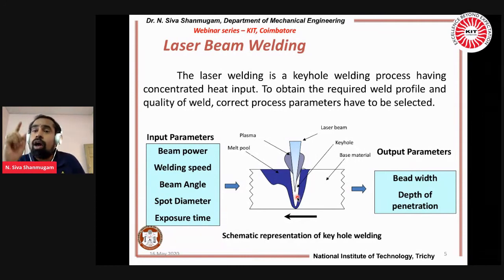10 power 5 watt per centimeter squared. So it is a very high heat and a very high energy density. If you are focusing a very high energy density onto a very small point, it will directly pierce the material. After piercing, the material encircling the laser beam will be partly vaporized because of absorbing the very high heat from the laser, and because of this absorption, it is converted from solid to liquid, liquid to vapor, and this vaporized material will create a plasma plume.